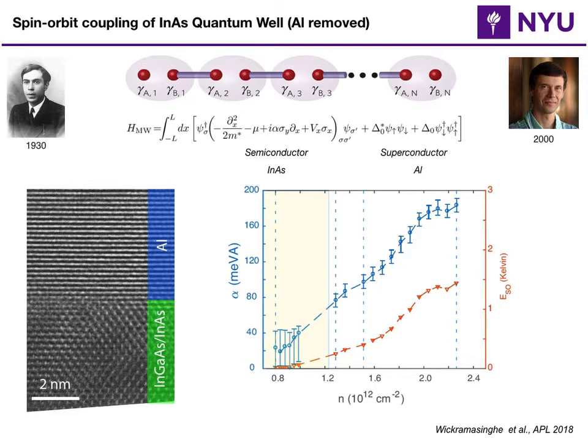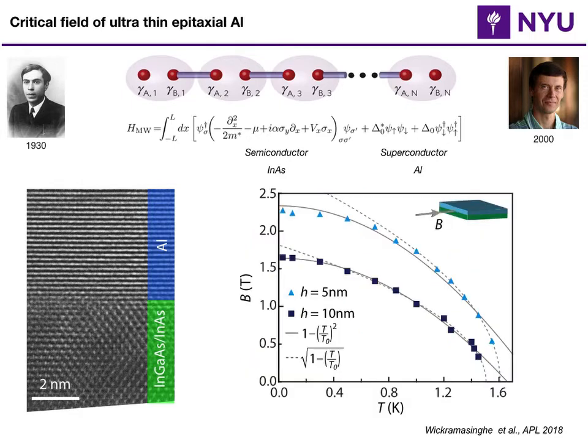And if you want to know the energy scale of this spin-orbit coupling, it can get up to about 1 or 2 Kelvin. So this is quite substantial for this physics. Now we have to make sure our superconductor can stay alive as we apply an in-plane magnetic field. And as I mentioned earlier, we do that by making the aluminum very thin, because the field that we need is in the plane.